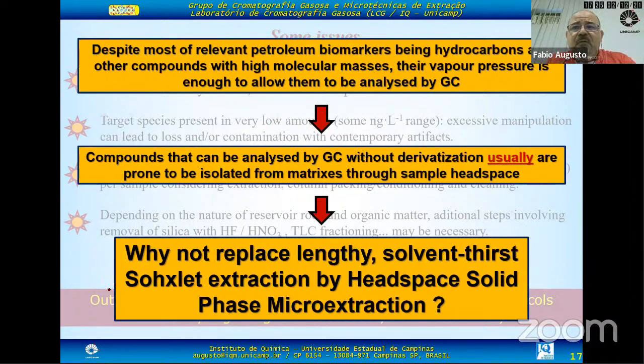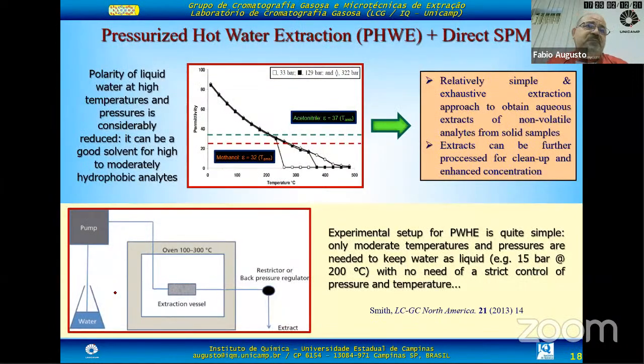So if it's possible, why not replace Soxhlet extraction here by headspace solid phase microextraction? Well, there are two forms of doing that. The first approach we've been using is combining pressurized hot water extraction with direct solid phase microextraction. First, extract the hydrocarbons from the rock samples using subcritical water at high temperatures, and then stick a fiber in this water extract, collect the hydrocarbons and analyze them.